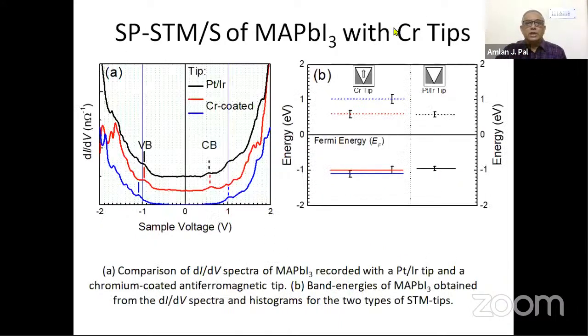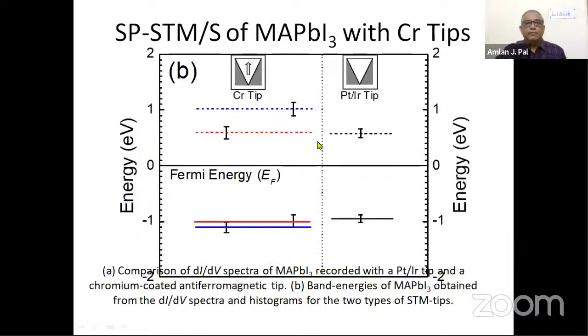Why is it? The plot is something like here. With the platinum iridium tip, that is a non-magnetic tip, we get only one level. But with the antiferromagnetic tip, we see the Rashba band split. We see both the states here and both the states here. The red color means one type of spin, and the blue color means the other type of spin. As you see, the inner of the two states have a similar spin state, and the outer of the two states again have the same spin state.